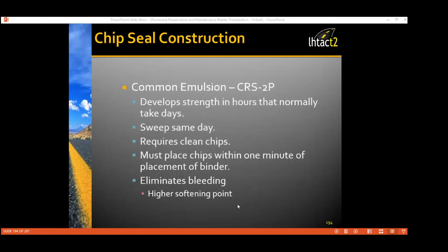So asphalt emulsions are kind of all over the map. There's different grades that you can use. So investigate what works best. This is a popular asphalt emulsion. It's a CRS-2P. P stands for polymerization. So it's got some polymer in it, kind of sticky. It will help develop strength. In hours, it'll cure out real rapidly rather than taking days. And so you can sweep this stuff the same day.